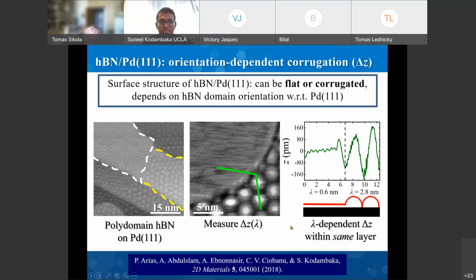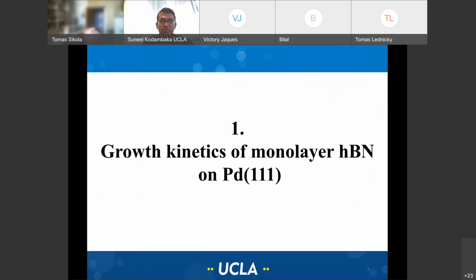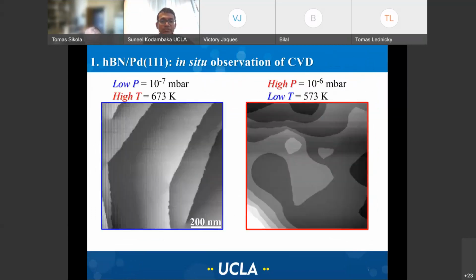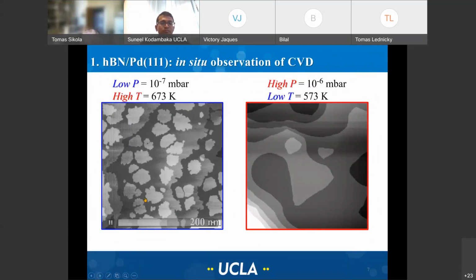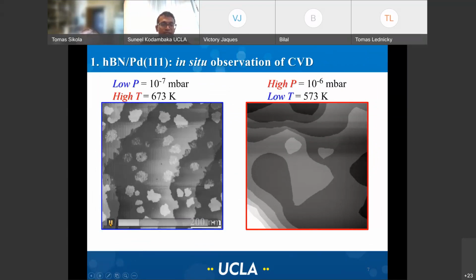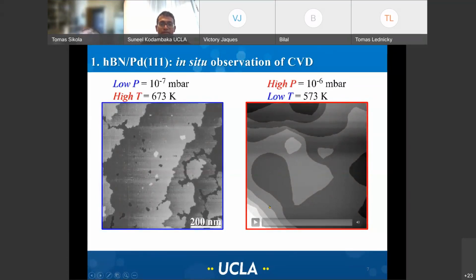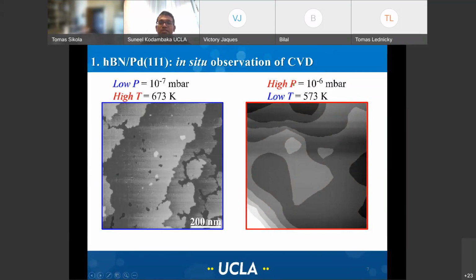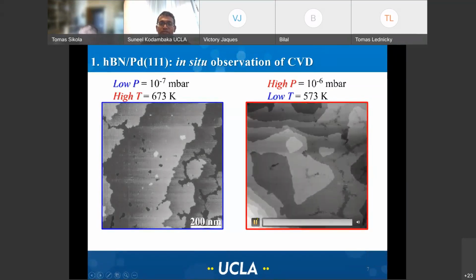Okay, I won't go into those details. I quickly wanted to show you how these hexagonal boron nitride layers grow. Here is one example: we start with bare palladium and we introduce borazine. Here are islands of hBN that form, and eventually you form a complete monolayer. And here is a slightly different experiment, done at a different borazine flux and slightly lower temperature. So we start with clean palladium, and once we introduce borazine, we again form a complete monolayer. But the way these monolayers form is different.